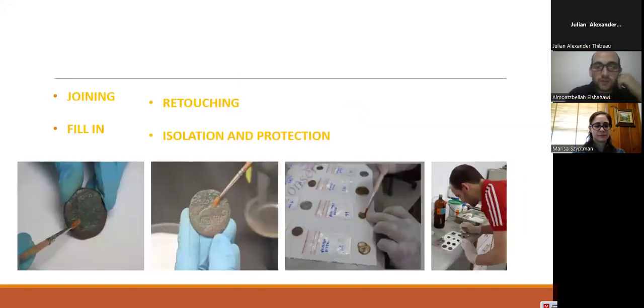For joining, if you have a coin broken into two pieces or three parts, you can join these coins using Paraloid B-44, 50% in acetone. And also if you have gaps or holes in some coins, this will affect the structure of the coins and will cause loss, or it will make the coins break. So you have to fill this with Paraloid and microballoon B-44 40%.